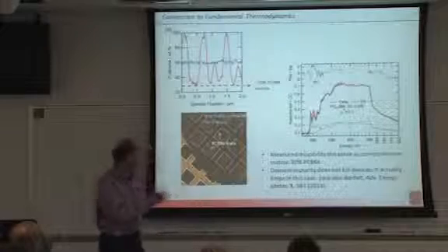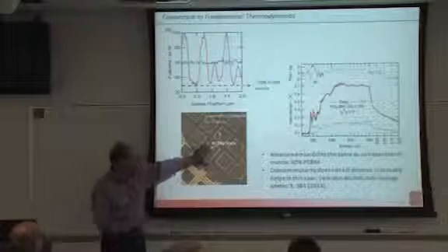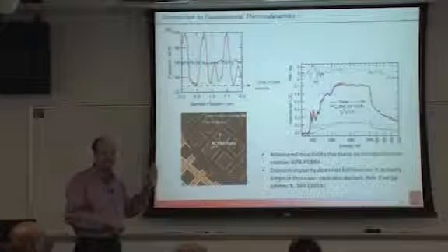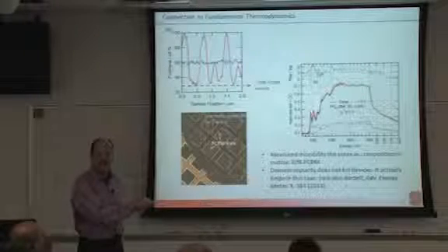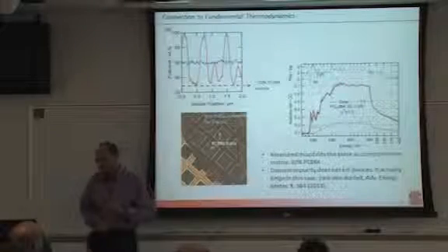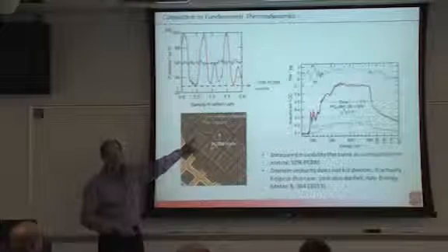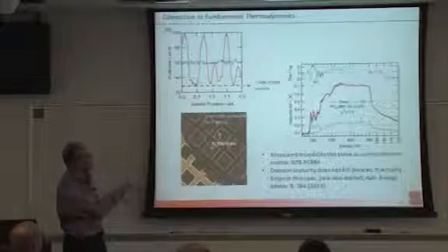And so if we aggressively anneal these devices for 5 days, so this is now at a temperature where you wouldn't create the device, but it's nonetheless interesting that in PBDB-T, the miscibility residual fullerene measurement that we have next to this PCBM crystal is 30% PCBM, and that is essentially what we have in the matrix